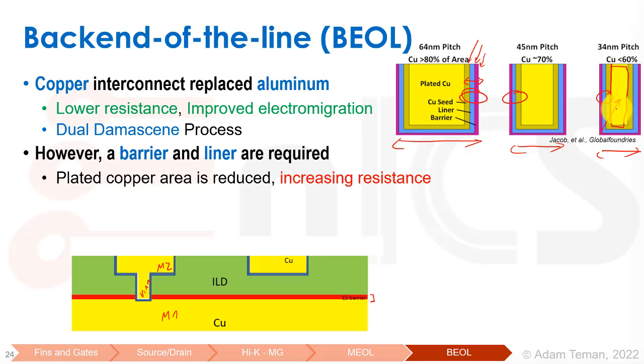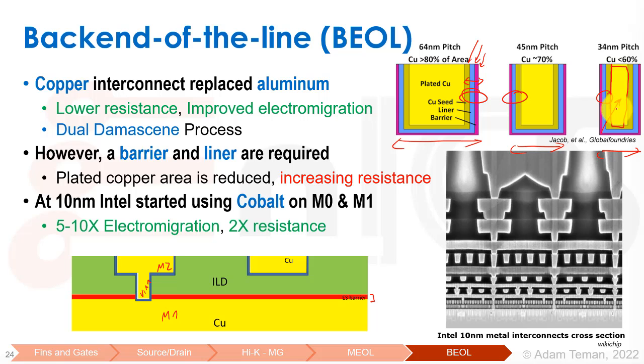So that's really bad. The answer to that is that at the really tight pitched metal layers, which are the low local interconnect layers, copper is not good anymore. Actually, cobalt and ruthenium and these types of materials, even though they have a higher resistivity, when you take into account the barriers that are needed, which are not needed in cobalt, then you actually get better resistance with cobalt, and you get much better electromigration protection. So Intel already put cobalt into their chips at 10 nanometers, and other fabs have been doing it also since then.